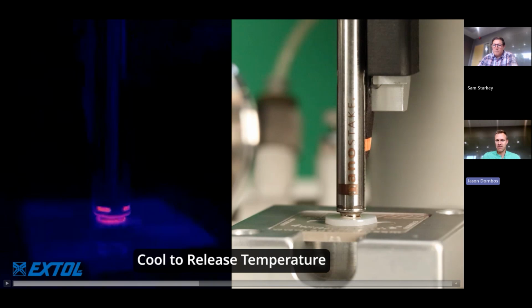How does the rapid heating and cooling affect the tool life? Yeah, we've done a lot of studies and have a lot of knowledge now based on the fact we've been producing these for, like we said, about 7 years. And really the heating and cooling is typically not the weakest link. We did early on make a change to the pogo pins inside the module, which now we're seeing much longer cycles on. So there are some contact points within the module that touch off on the heater core. Those were gold plated. We've made an internal running change now to those. And so we have hundreds of thousands of cycles being run on these at customers, sometimes millions.